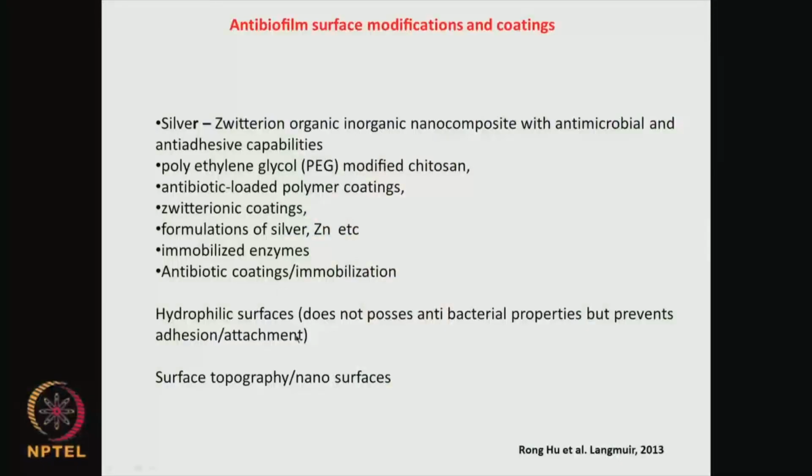So, one can develop such surfaces or modify the topography of the surface, creating indents, creating nanostructures. By doing this, you are preventing bacterial attachment. The question being asked is, why do shells, which are living all the time in water, not get biofouled or form biofilm, or why are there no biofilms on sharks and fish? That is because they have a lot of nanostructures present on them, which prevent bacterial attachment and prevent large organisms from settling down.